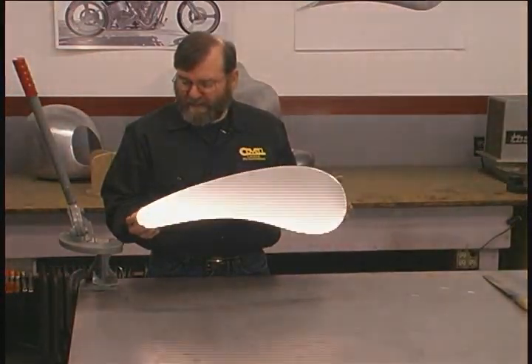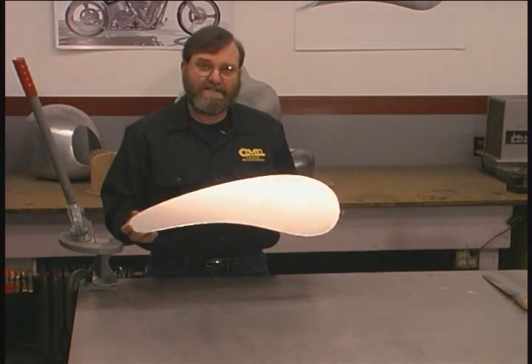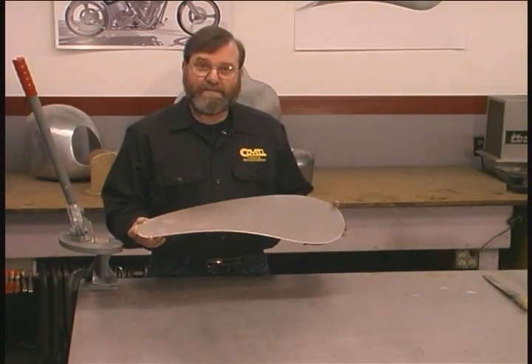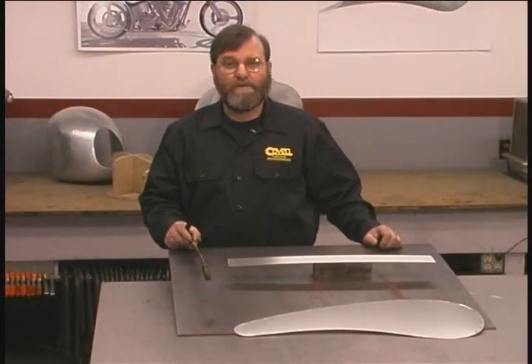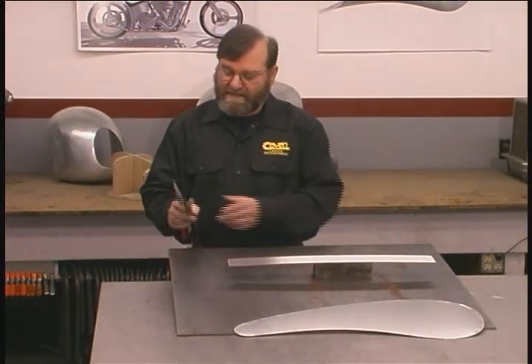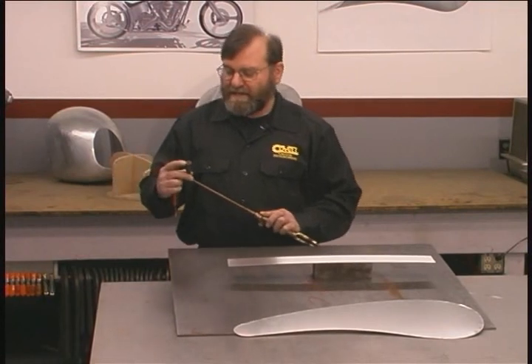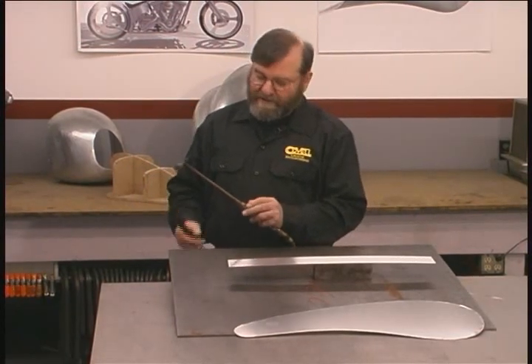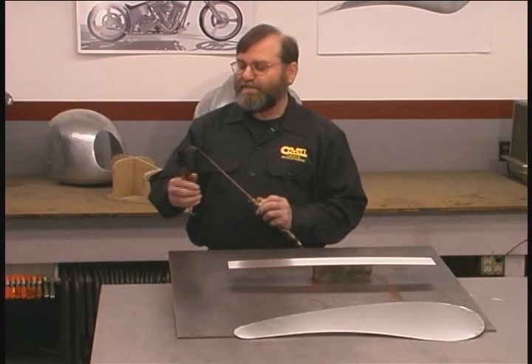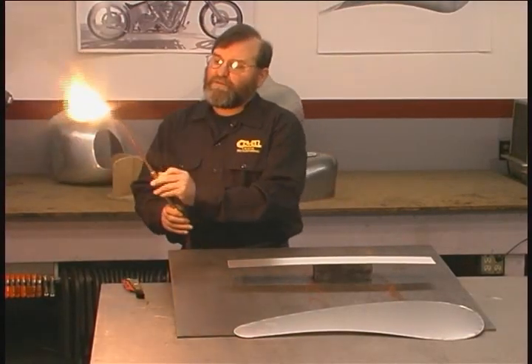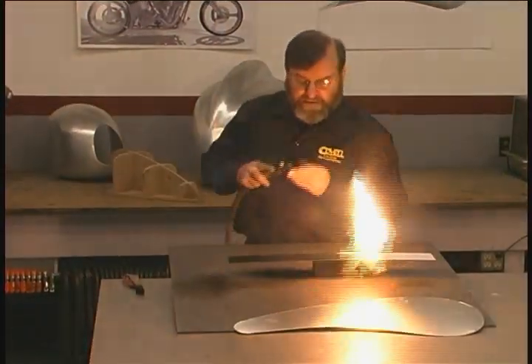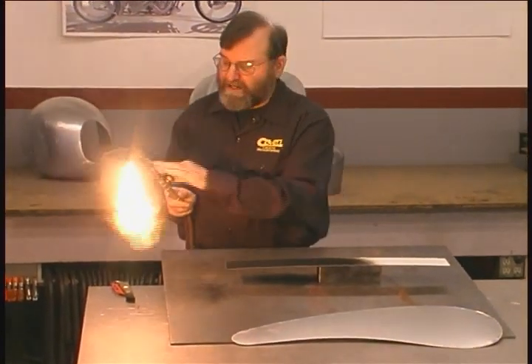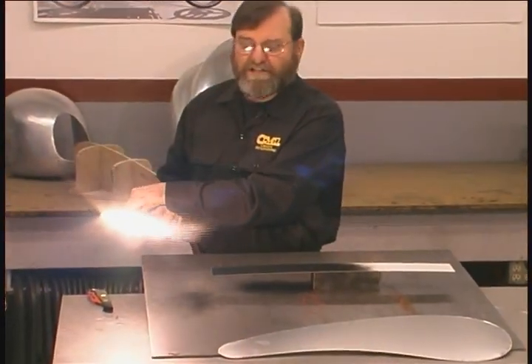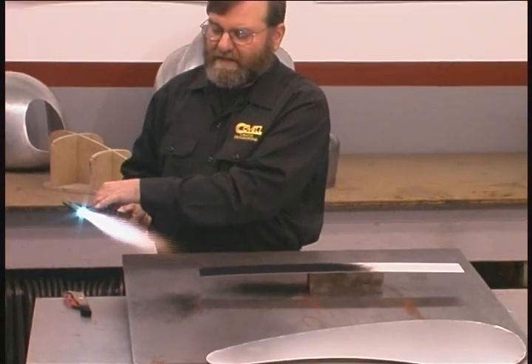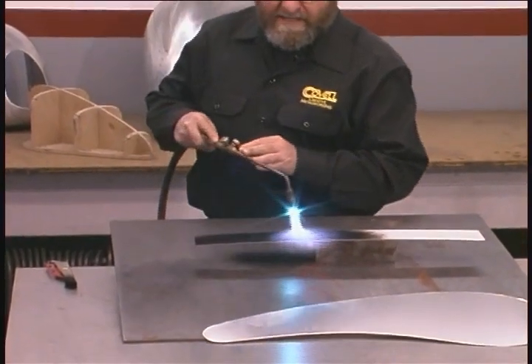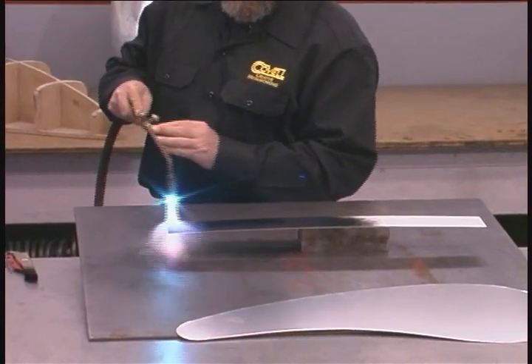Every alloy of aluminum has its own temperature that causes it to soften. With this material, it's about 800 degrees. Okay, let's do a demonstration of the annealing process. I'm using a rosebud tip, a multi-orifice tip. I'm going to turn on a lot of acetylene and light the flame. Now with this pure acetylene flame, I'll put a coating of soot on a piece of metal. Now I'll add oxygen so that we have a neutral flame, and we'll start heating the piece of metal until the soot burns off.